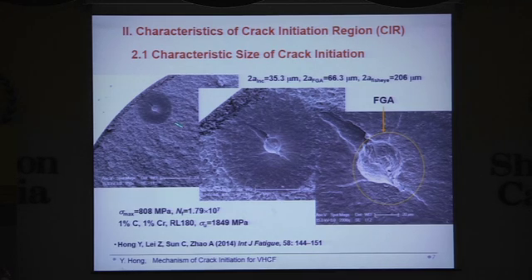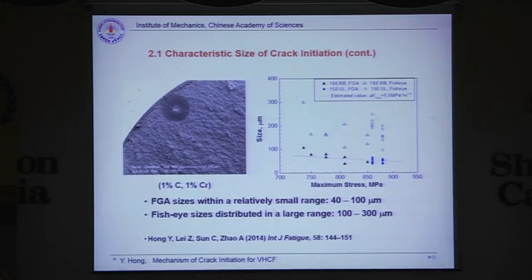Again, this is an example showing that the crack initiation of very high cycle fatigue is from the subsurface of the material. For this case, we see a morphology called fisheye, and in the center is a rough surface called fine granular area, FGA, due to an inclusion as crack origin. For this case, the size of FGA is about 66 microns, and the fisheye is about 206 microns. So now we may have an idea of the size of FGA and fisheye. We measured a number of specimens and the size of FGA is between 40 and 100 microns.